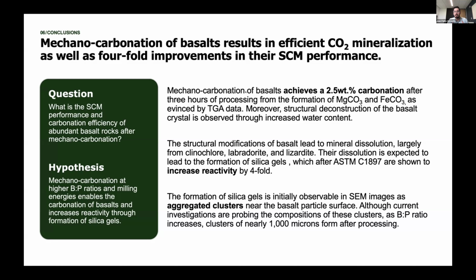What we found is that the milling energy doesn't really matter as much. It doesn't have such a big significant influence on our results. And that, yes, we can actually carbonate these basalts, achieving 2.5 weight% of CO2 uptake and achieving more than a fourfold increase in reactivity, making these mechanocarbonated basalt materials a good option for cement replacement.